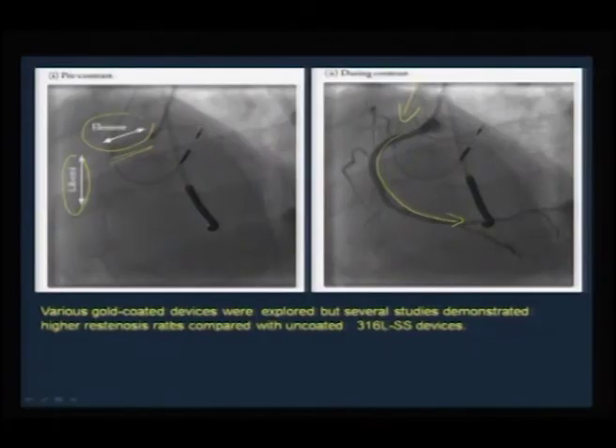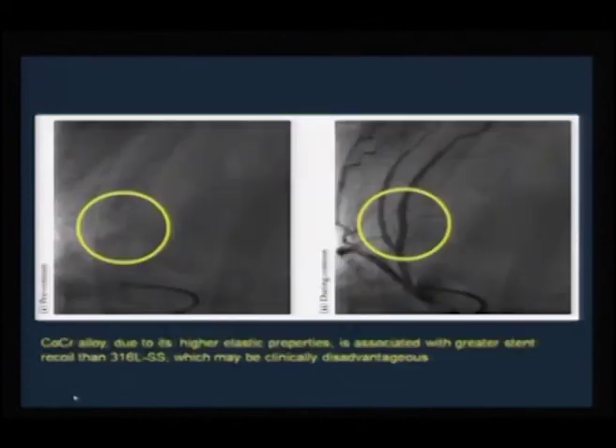But people have also used many other coatings on these devices. For example, gold coated devices have been tried, but although gold is a safer metal, biocompatible, it seems that restenosis is appearing at a higher rate when it is gold coated. So, gold coating is actually not prevalent these days, especially on these stent alloys.